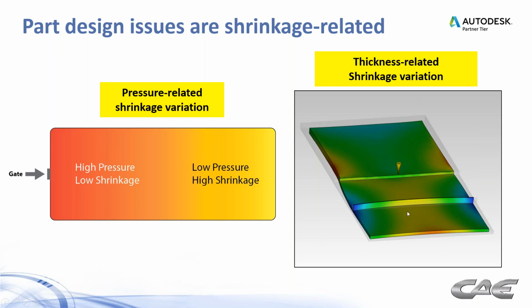Here's just a simple mock-up of a part that has 2 different thicknesses, and then also an even thinner rib on top of that thin section there. And you can see what happens here. When I exaggerate things, the thicker section, as you can imagine, tends to shrink more than the thinner section. And then when we put an even thinner rib on top of there, it shrinks even less and wants to hold its length.